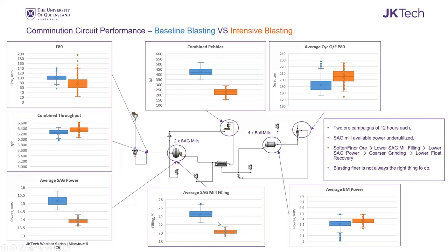This means two variables affect a coarser final grind size. One is a slightly higher throughput, but number two, very important, the shorter residence time given by the lower mill filling that did not promote too much fines generation. So then the transfer size to the ball milling is coarser, and the ball mills get a coarser final grind size. And this negatively affects flotation performance.